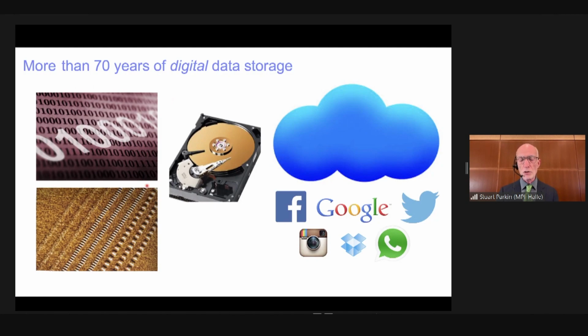On the left-hand side, you can see an image of some of these magnetic disks shown as white and black regions, magnetic moment pointing up or pointing down. And you can see, from the right to the left, these regions are being shrunk in size. And over the last 70 years, these regions have shrunk by many orders of magnitude. That means we need new means of both writing and reading this information.